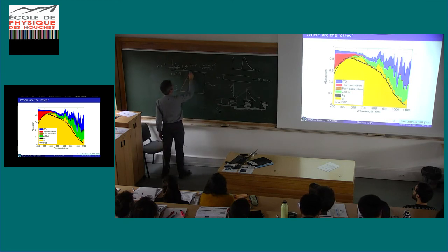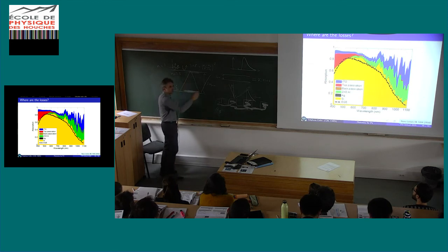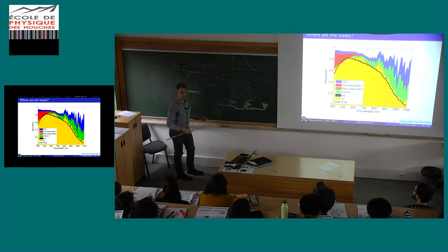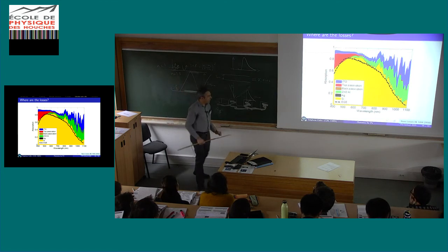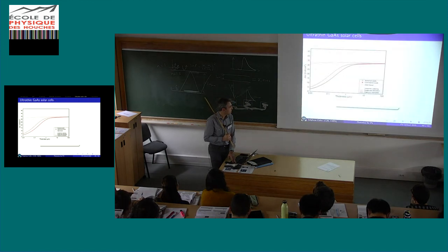Imagine you have a path of light here, and actually here you have some parasitic absorption in the layers. So you see these layers, the photons see these layers several times, and so you absorb more, you have more parasitic absorption than in the same structure with a single pass absorption. And so finally, that's why most of current solar cells are far from the limits because of this parasitic absorption. And you can find very similar features for other more conventional solar cells.